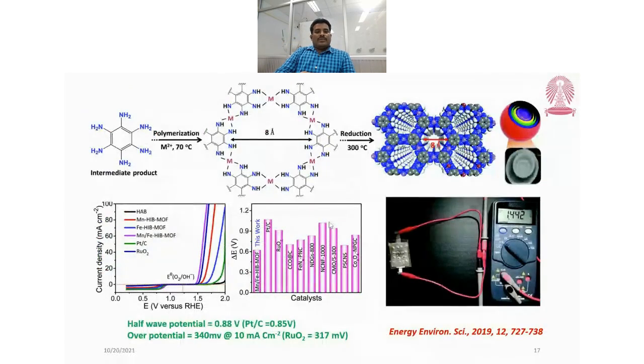Similarly, another interesting MOF is a dual linkage MOF, synthesized from hexaminobenzene. It gets polymerized with iron and manganese to form a well packed structure as well as hierarchical porosity. So this is most important. This is a bifunctional catalyst, and they compared its efficiency with a precious metal catalyst. It is nearly equal, the efficiency is equal, and they analyzed battery performance also. It gives a better performance towards a zinc battery.